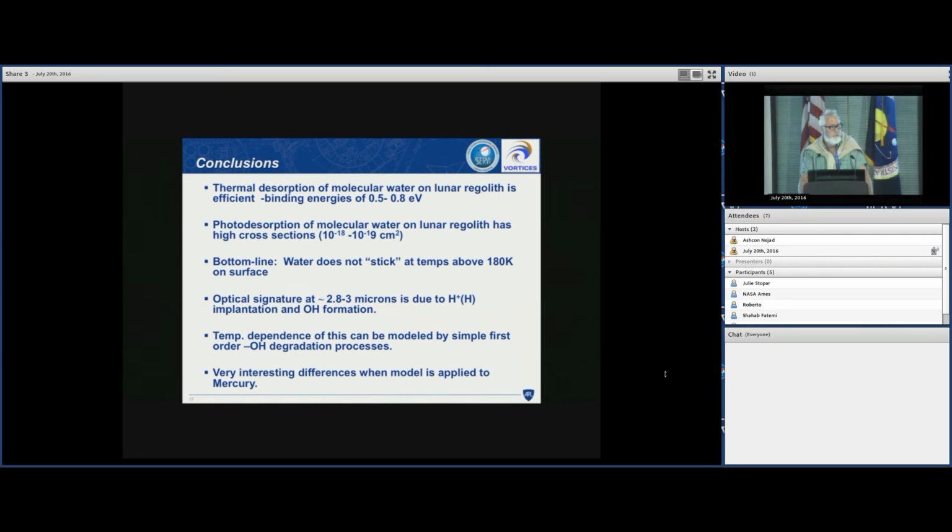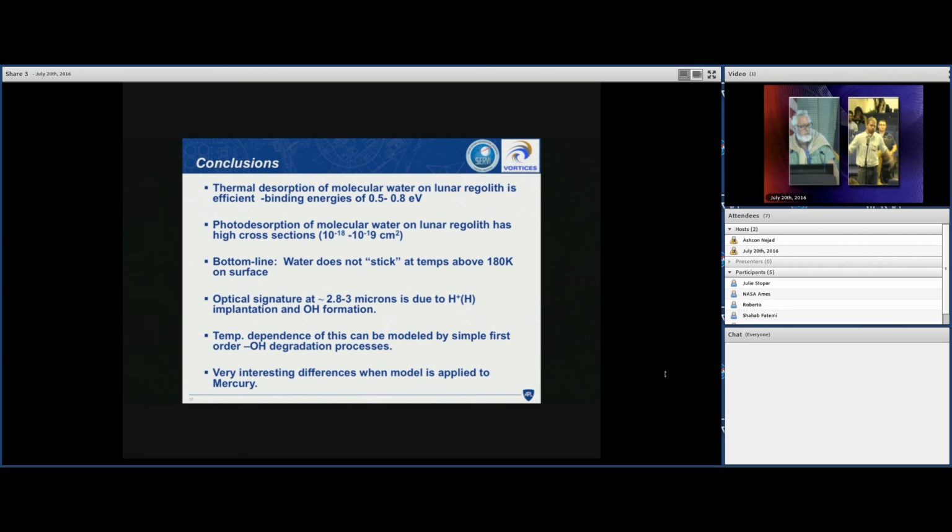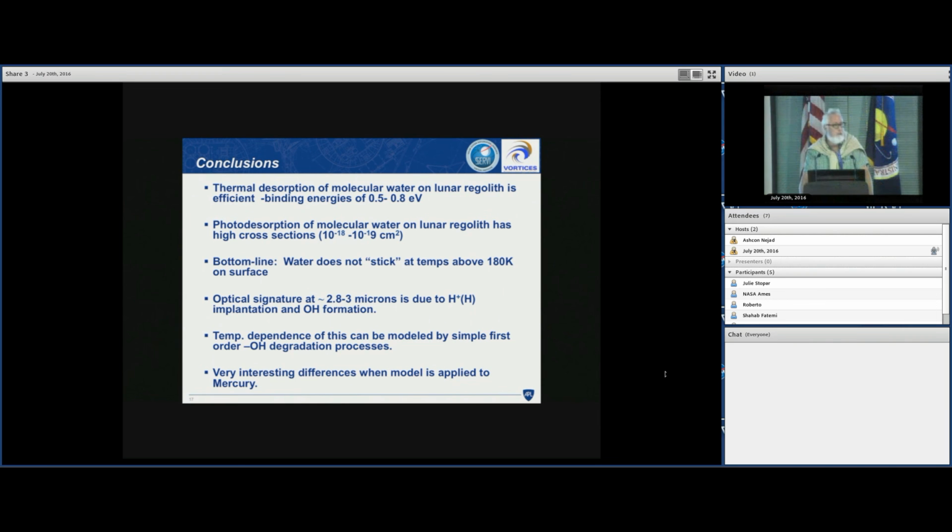But that could be due to contamination from Earth's atmosphere as well, right? Well, yeah, sure, that's what it's from. It's water interacting with the mineral because they're very active. And so that's actually why we did the very first experiment and took it to 750 to move stuff off. And then we do all the experiments at 550, because then you've removed all of that, right?